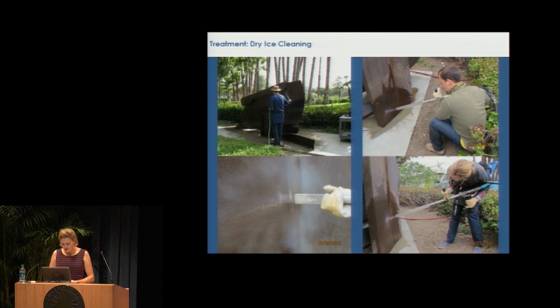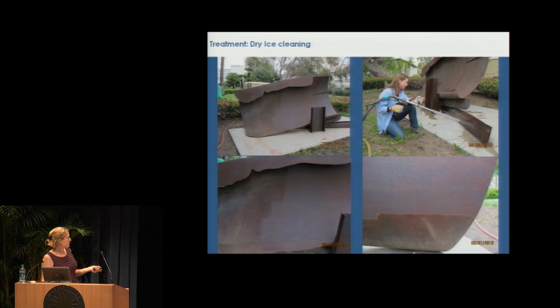For most of the sculpture, we used a pressure between 60 and 80 psi, so quite high, combined with a medium particle feed and the long, narrow nozzle, which you see here. This nozzle turned out to be the best for us.